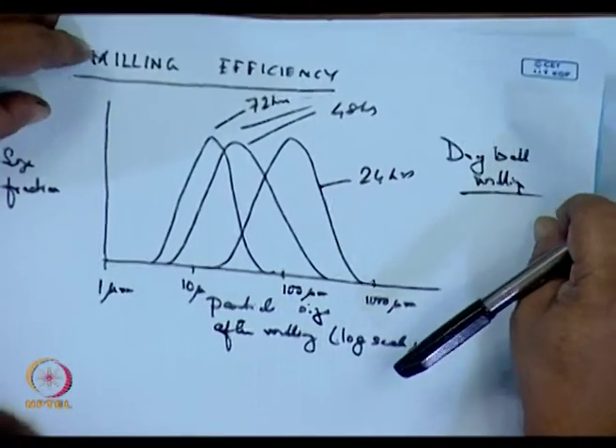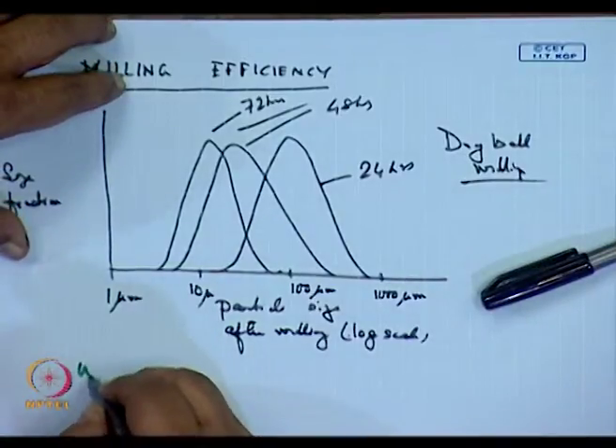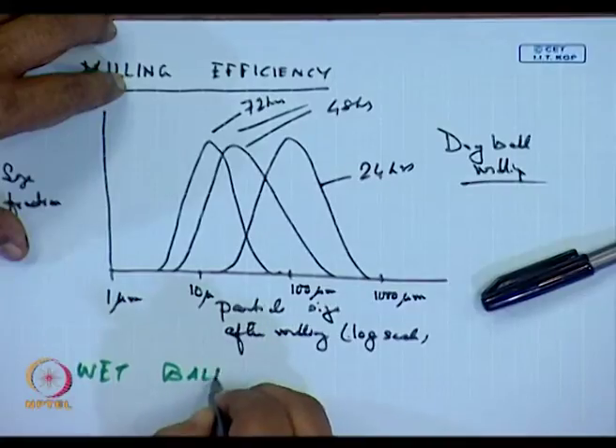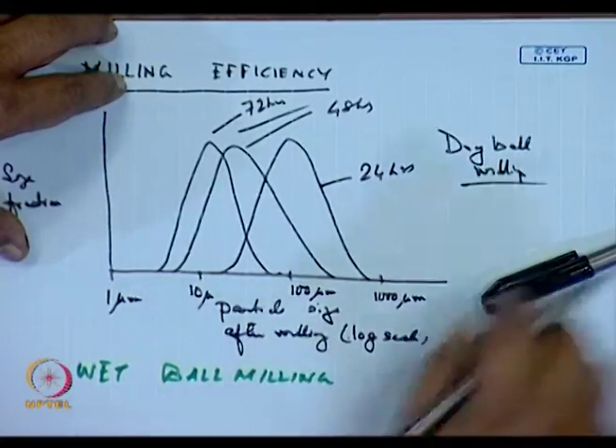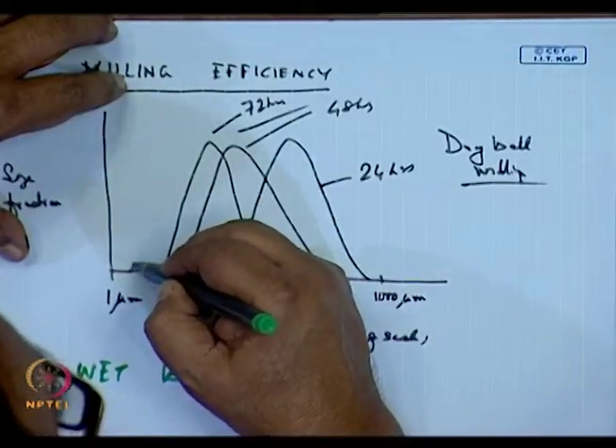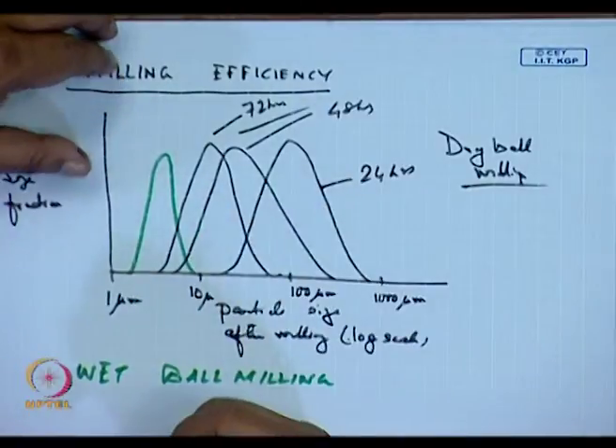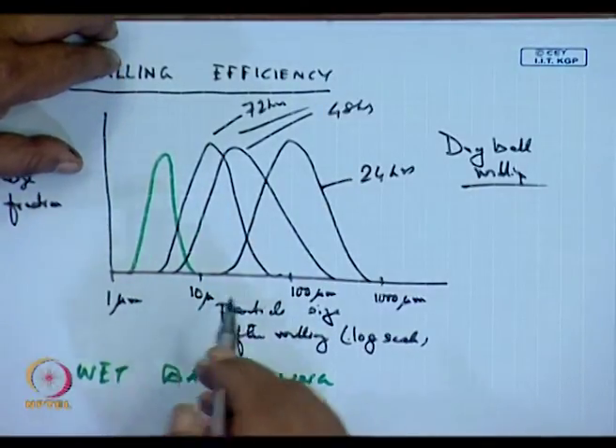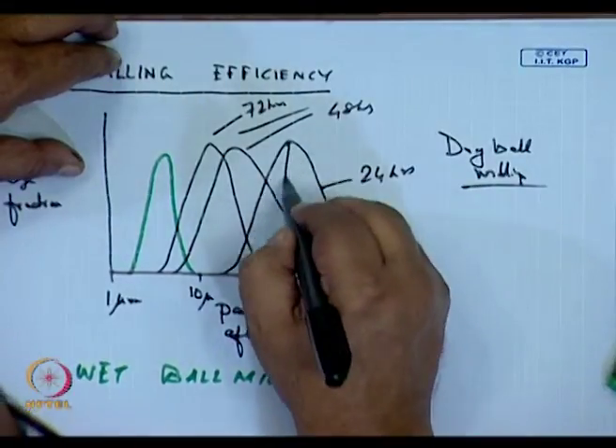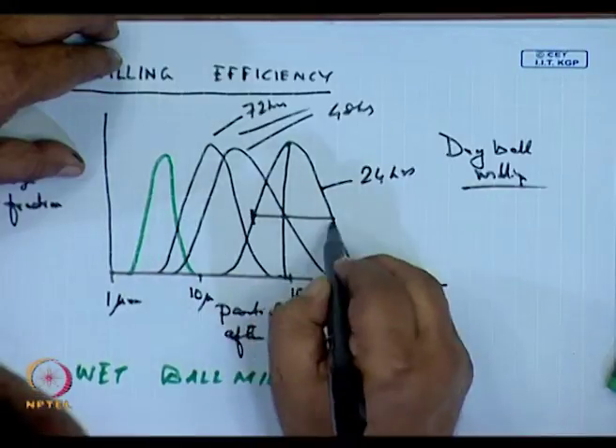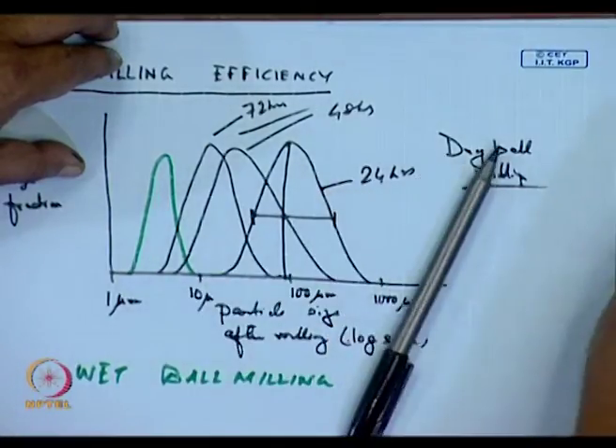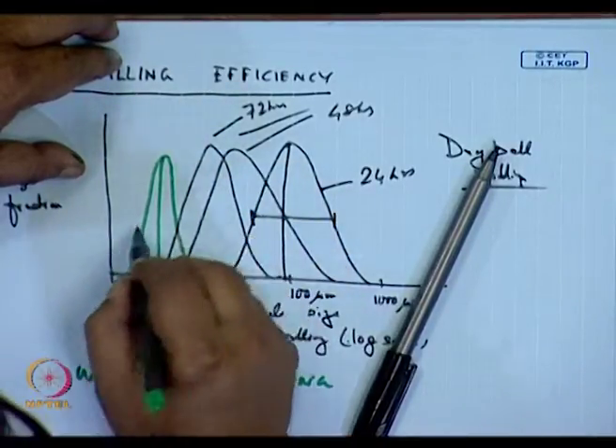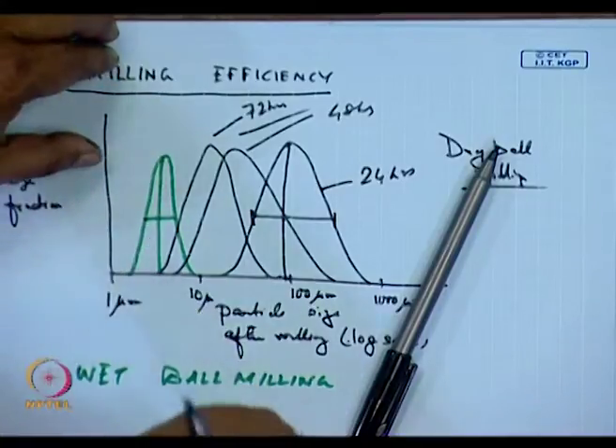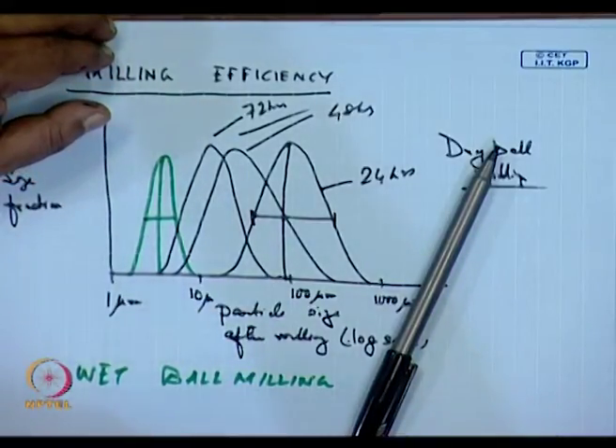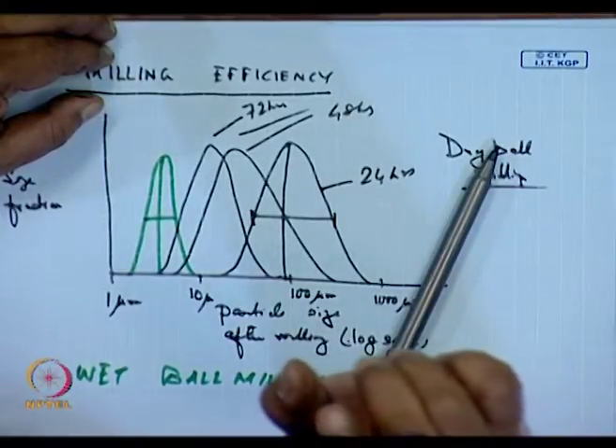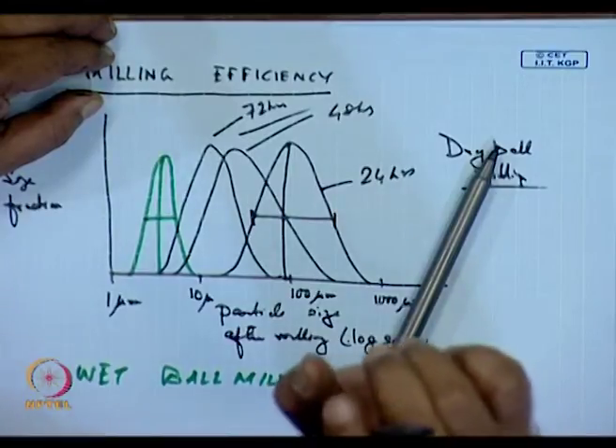In wet ball milling, I may have powder sizes down to here. Now, the first change you see here: look at the size range at half height, this is wide, but over here it is much narrower. So, in wet ball milling, one of the things that we can achieve is a narrower size distribution with particle size being finer than with dry ball milling.